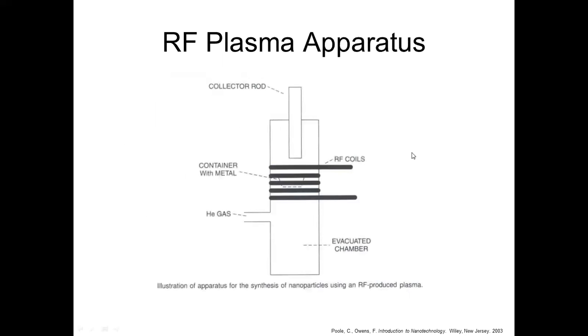In the case of aluminum nanoparticles, oxygen forms a thin layer of aluminum oxide around the particle, which prevents further growth, aggregation, and agglomeration. RF plasma synthesis is a very popular method for creating ceramic nanoparticles and powders. However, it does feature a very low mass yield, so we can't produce things by the millions of tons. This shows a schematic example of the system from the Poole and Owens book, a useful reference on nano manufacturing.